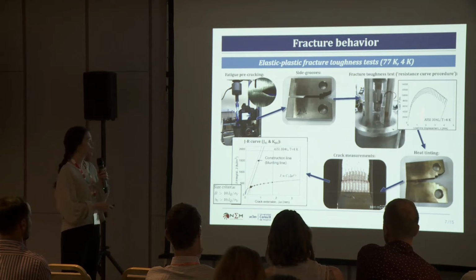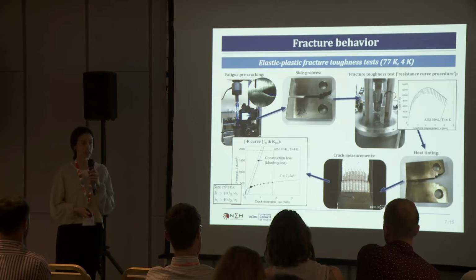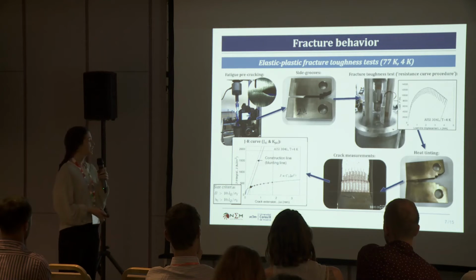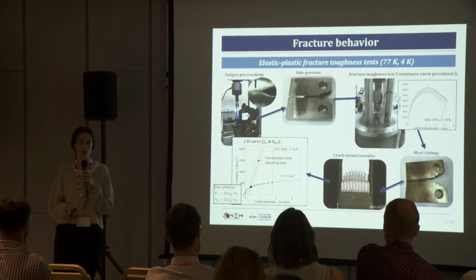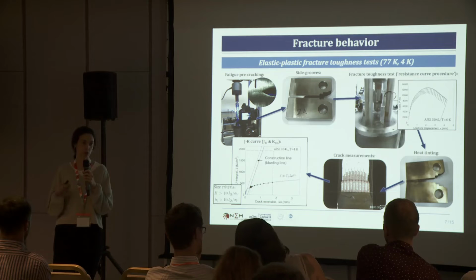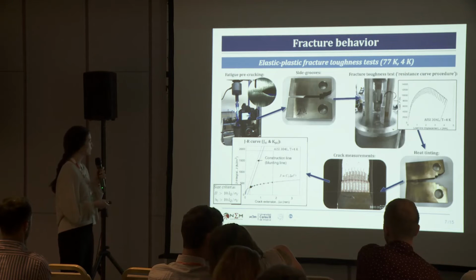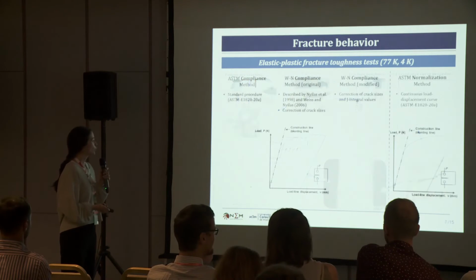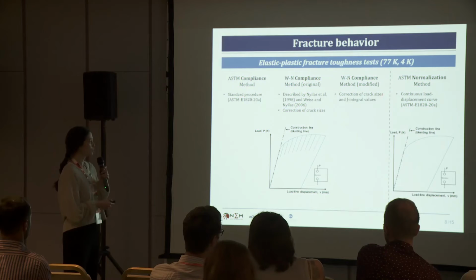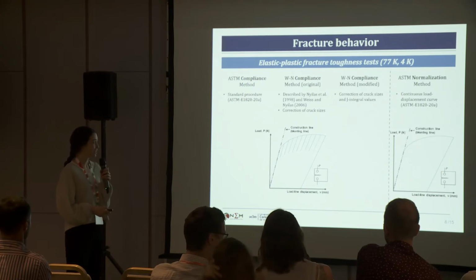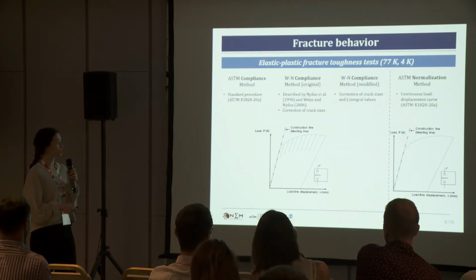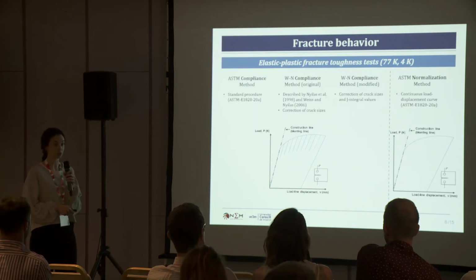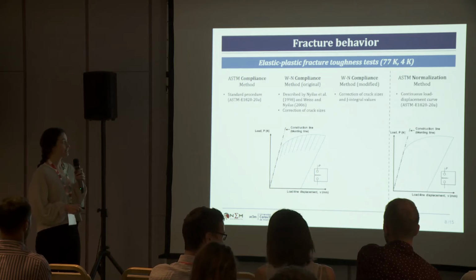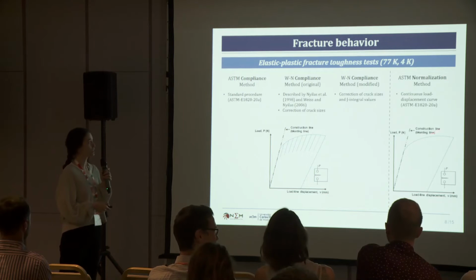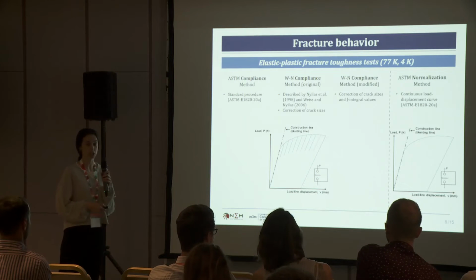So the whole procedure, I have done it according to the standard ASTM E1820, but the construction of the J-R curve I have been using 4 different methods. So we are going to compare it now, okay, to see what is the difference between them. So 3 of those methods are compliance methods, which means that we need to perform unloading, reloading sequences during our test in order to estimate the crack size. And then the last method, the 4th method, is a normalization method. We are using the one described in the standard.